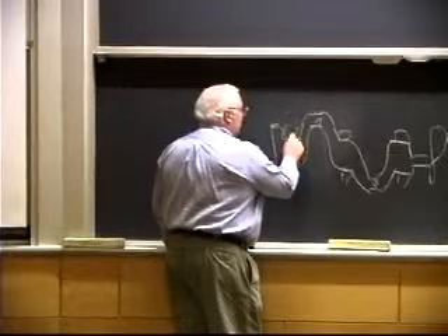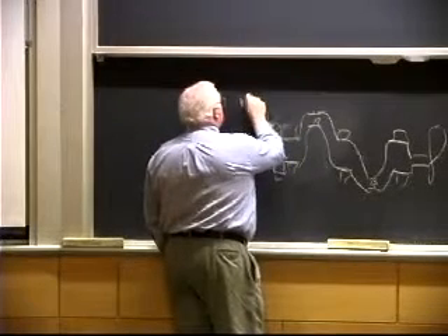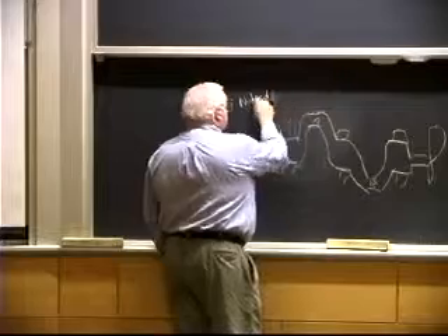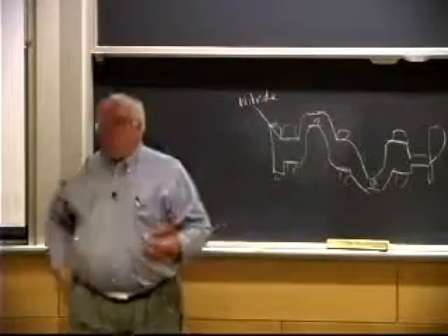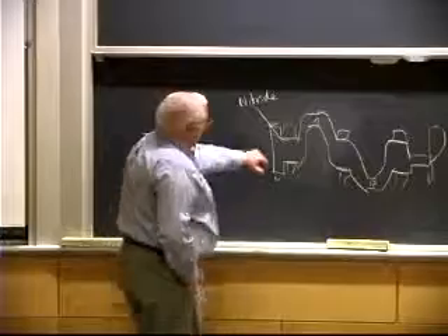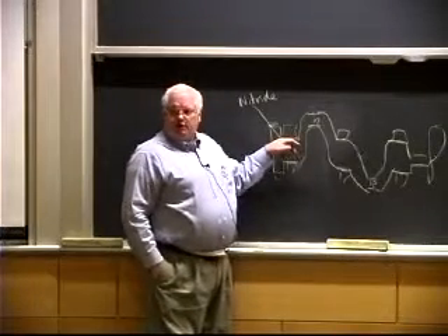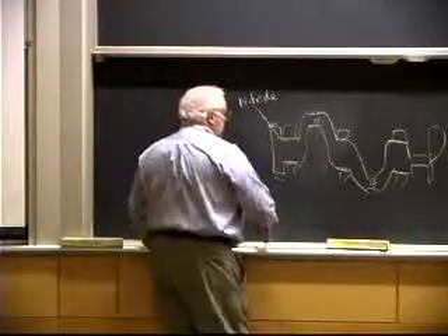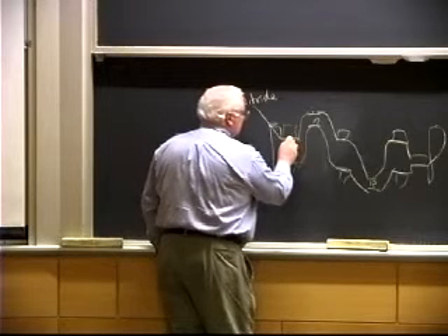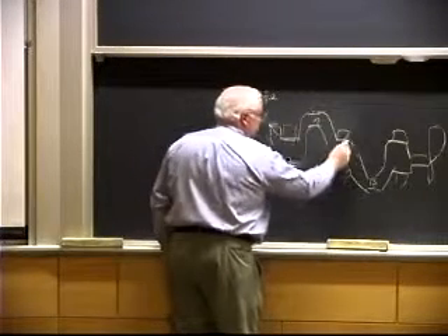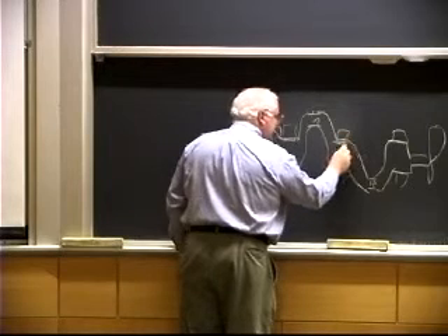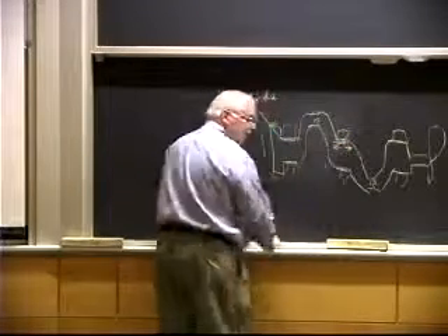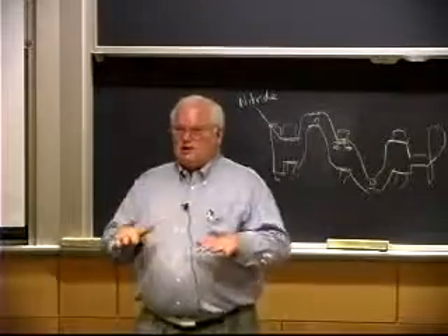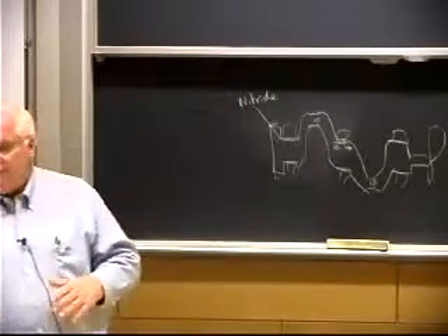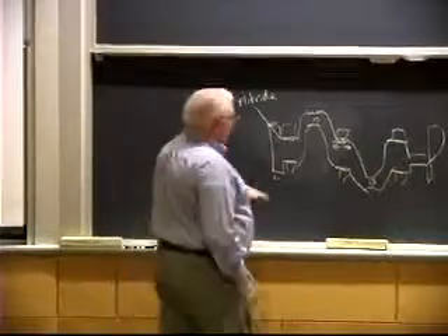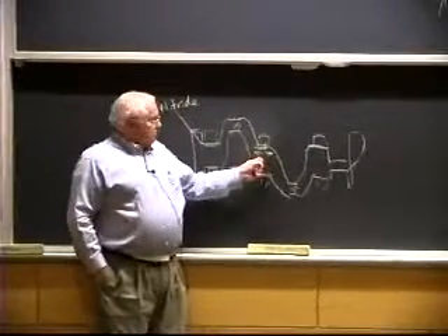So for wear resistance, they nitride the case. This is a steel part, and they take an ammonia atmosphere and diffuse nitrogen into the surface. As they diffuse the nitrogen, it expands the surface and gives you very favorable compressive stresses. But if I get compressive stresses on the surface, you're going to get tensile stresses underneath the surface, because you have to balance the stresses. Compressive stresses on the surface are good for fatigue, but just beneath the surface, by a couple of millimeters, I'm going to have tensile stresses.